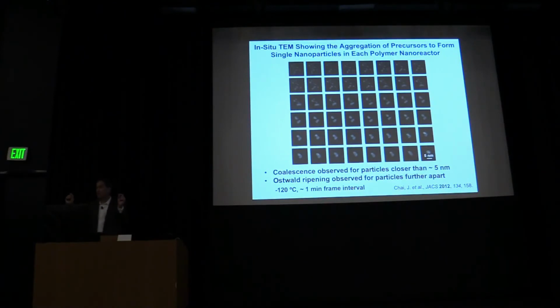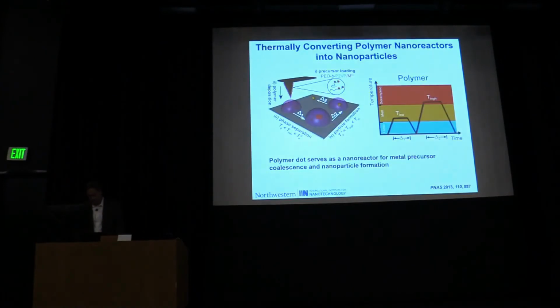And what you find is two processes are occurring. One is Ostwald ripening, where one particle is basically dissolving and feeding atoms to other particles. And the other is where coalescence is taking place and the particles are merging. If you study these, you can convince yourself that coalescence is observed as the dominant process for particles or nuclei that are closer than 5 nanometers apart. Further than 5 nanometers apart, the Ostwald ripening mechanism dominates. So one of the things that you get is the ability to study nanocluster synthesis in a really unique way, in a way where you can set up the conditions, dial them in, and drive the process.